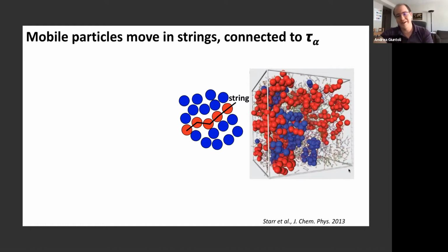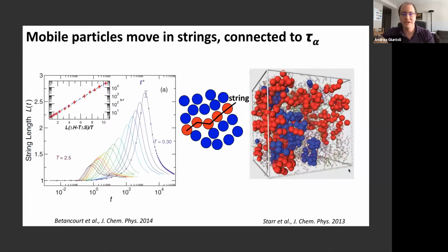And if you go back to the bar, that makes sense because these clusters of immobile particles are, say, people chatting with their friends or dancing still on the floor. And if you want to move around in the crowded environment, the easiest way to do that is to follow other people going in the same direction. And that's how a string is formed. It emerges naturally from this heterogeneous environment. And if you measure the length of these strings, you'll notice that it changes with temperature and it increases together with the alpha relaxation time, so that these two things are actually connected.